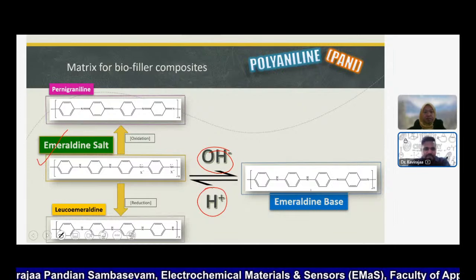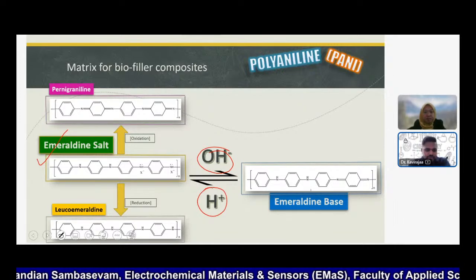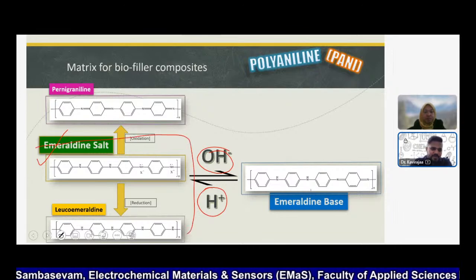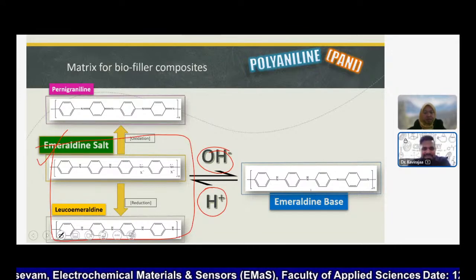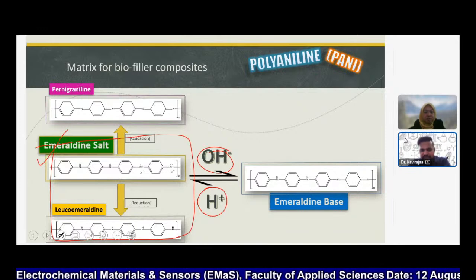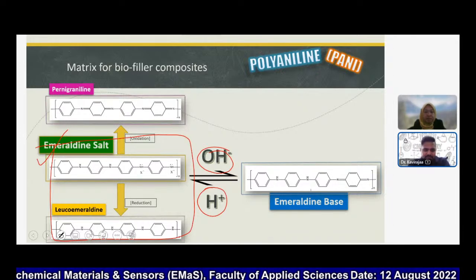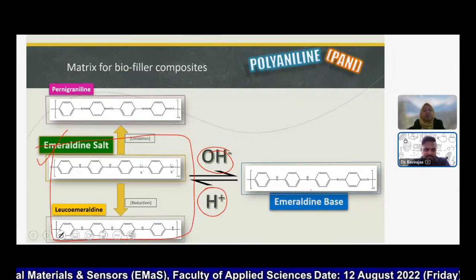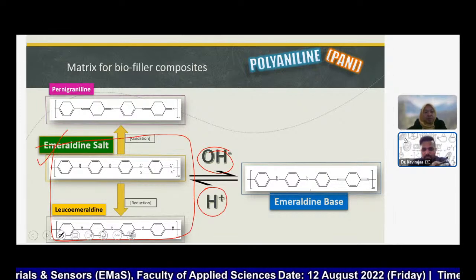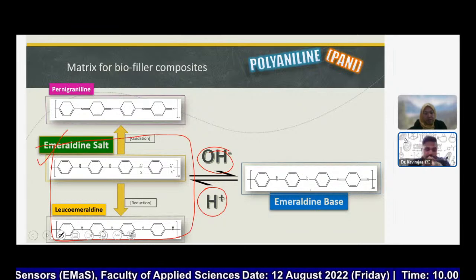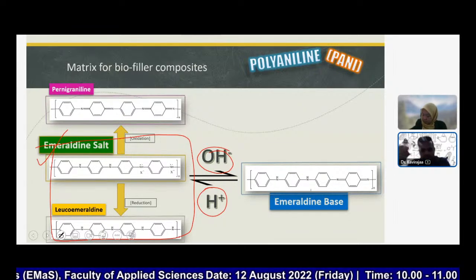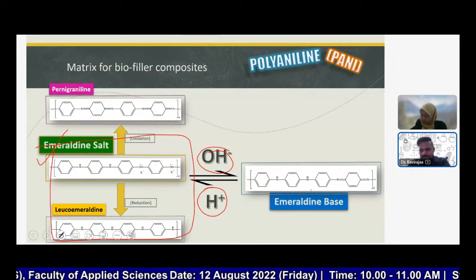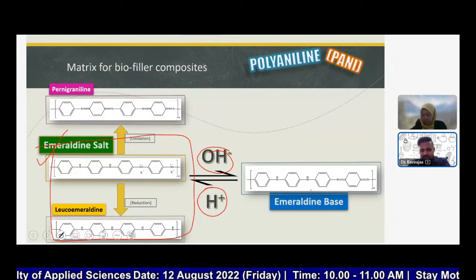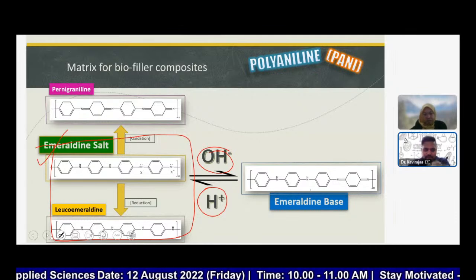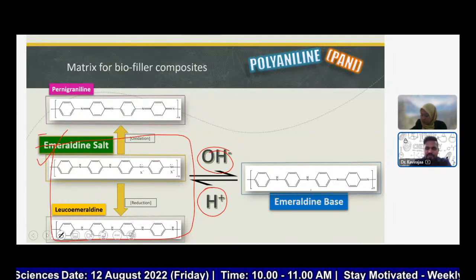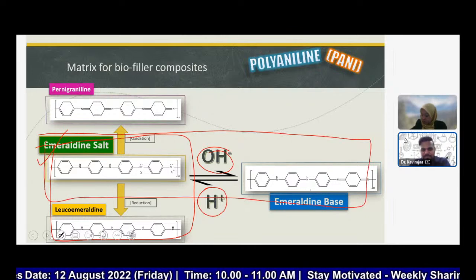On top of that, we also can fully reduce. This is the fully reduced part. If, let's say, we fully reduce this emeraldine salt, it will go into a pale yellow or colorless type of appearance of the material, which is leucoemeraldine. So my PhD work was focused on this aspect, which is emeraldine salt and leucoemeraldine. But then it involves some tedious work. So when I started my research over here, I don't focus on the leucoemeraldine, the fully reduced part. I just focus on this very simple acid-base chemistry.